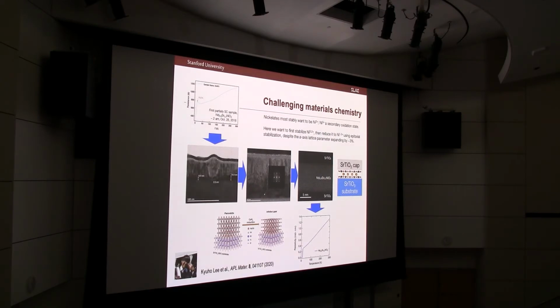Okay, so the strain that you're constraining with the strontium titanate is all lateral. It's all lateral strain. There's nothing going on vertically. Yeah, so that's a good point, actually. I won't go into the details, but for everything I'm telling you about, since we're in this thin film regime, the in-plane lattice constants are artificially constrained to the substrate. So it is not, let's say, the natural lattice constants of that system. So that might be important, actually.